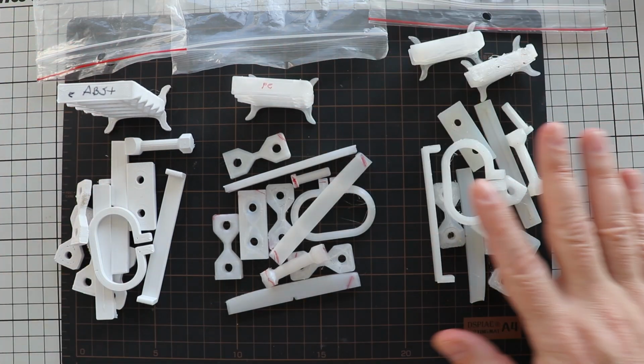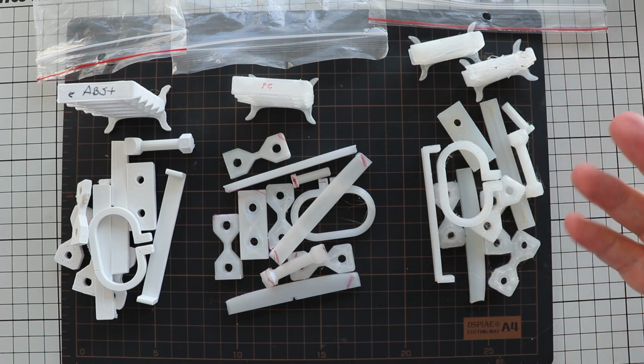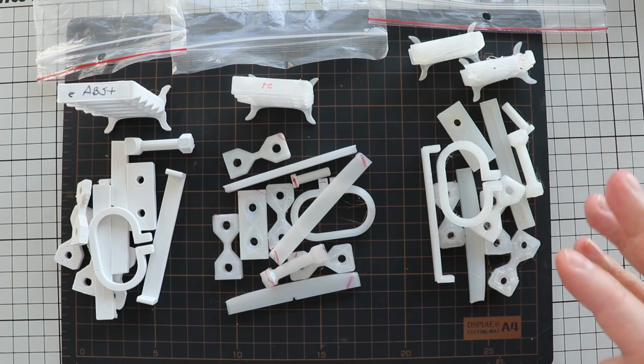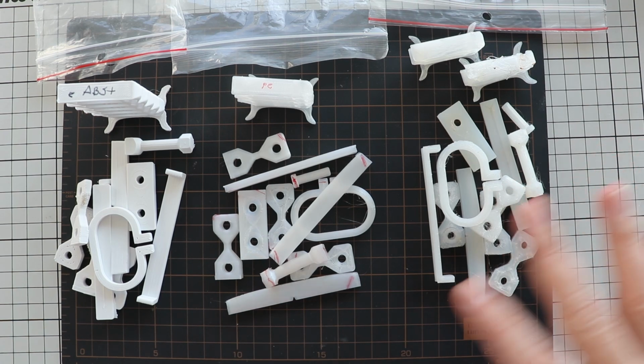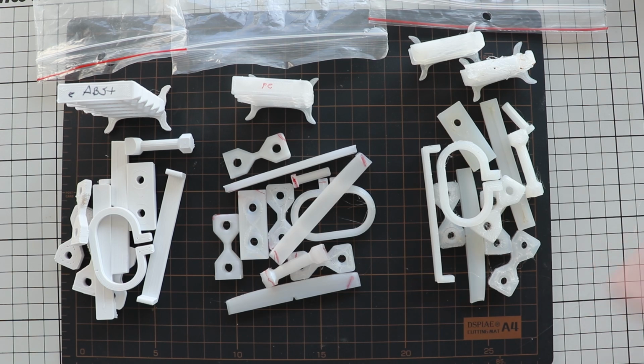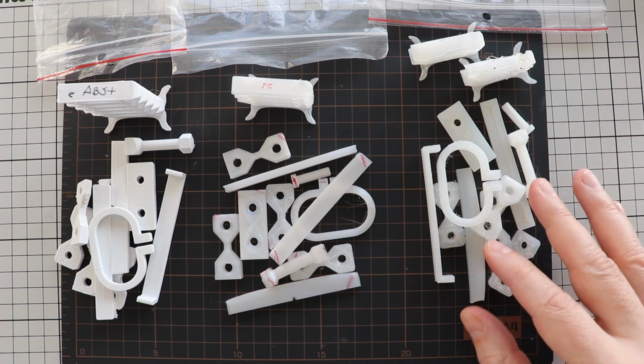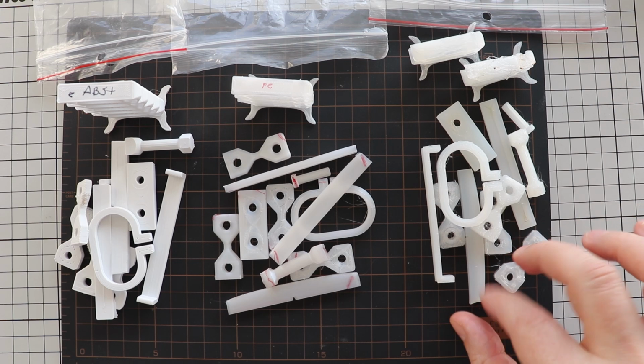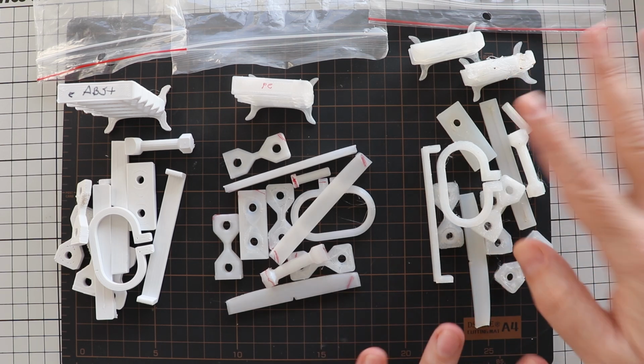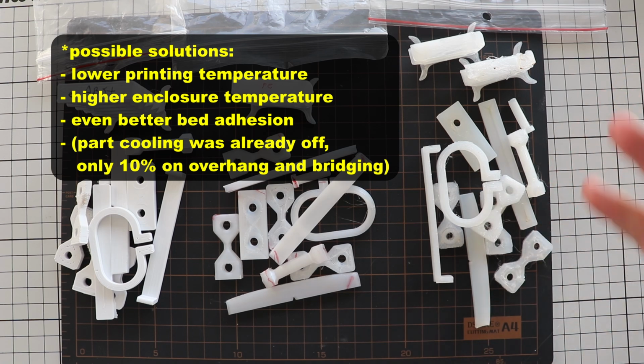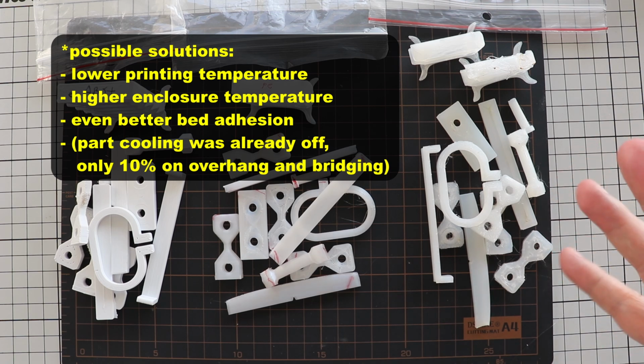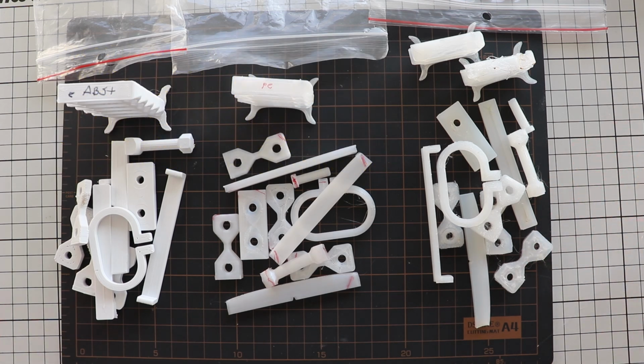And the hardest for printing was the nylon or PA, polyamide. The biggest problem was the warping. I thought the biggest problem would be the wet filament, but it was completely dry. I didn't hear any crack sounds or something like that. So this was dry filament. I could get a very good adhesion to the bed, but even so you saw it has a lot of warping. So definitely for printing nylon it needs a higher environment temperature. My highest was 46 degrees Celsius inside the enclosure, so it probably requires maybe even 50 or 55, but sometimes that is too much for the electronics, so it really needs some special printers for this.